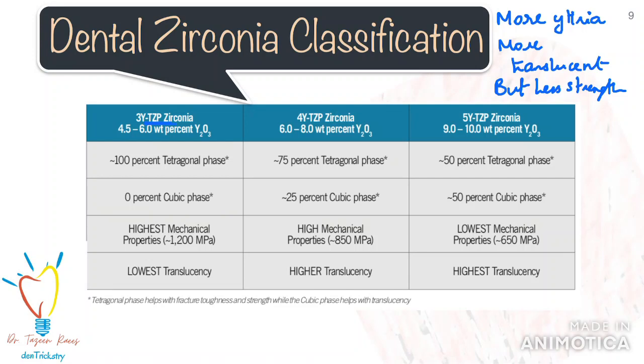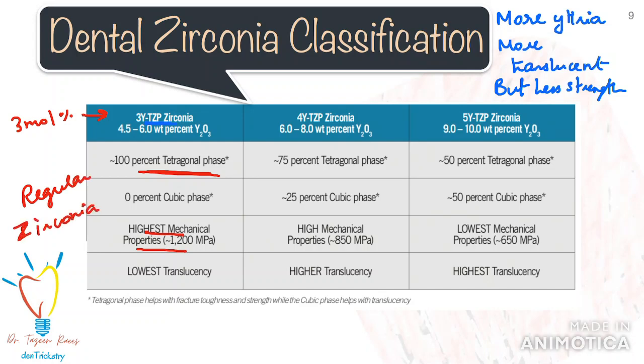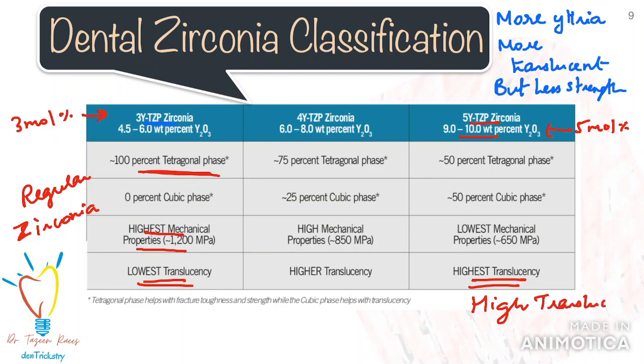The first group is strong but opaque. When 3 mole percent yttria is added, a 100% tetragonal phase is achieved at room temperature — called 3Y-TZP. This is the regular zirconia, a great option for posteriors due to its high strength, but with not-so-great aesthetics. When approximately 5 mole percent yttria is added, a structure of 50% tetragonal and 50% cubic phase — known as high-translucent or cubic zirconia — is produced. These high-translucent zirconias typically offer a lower fracture toughness comparable to lithium disilicate, though the aesthetics of lithium disilicate are still better.